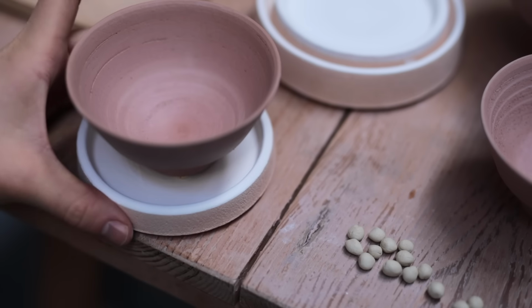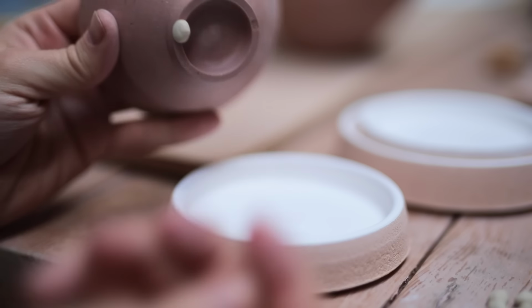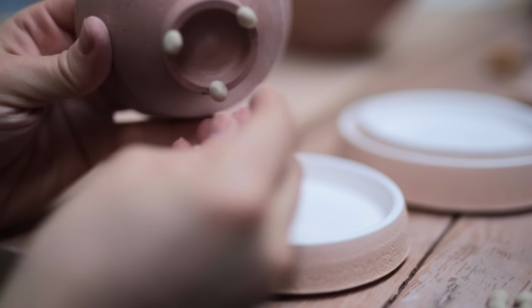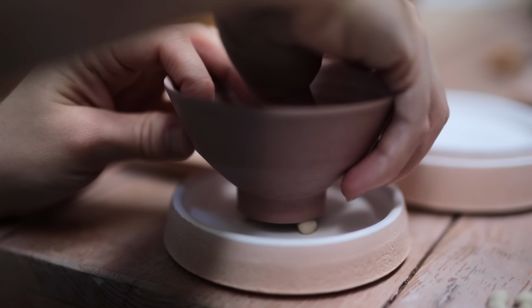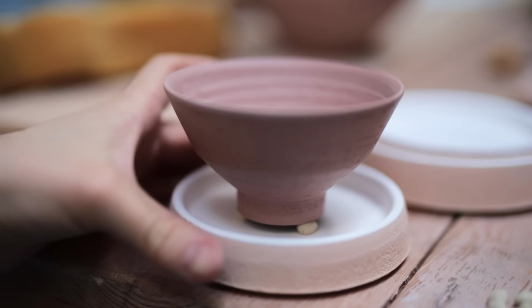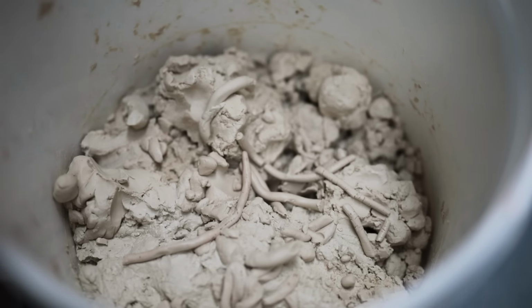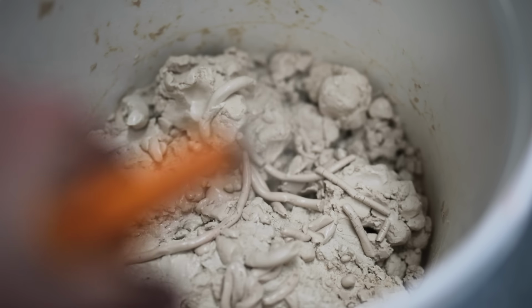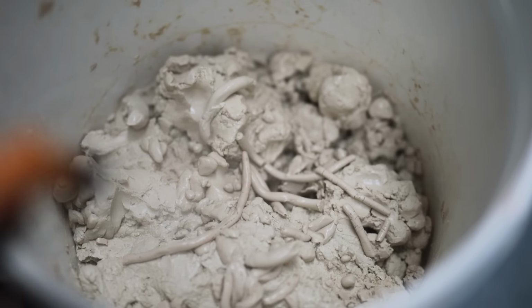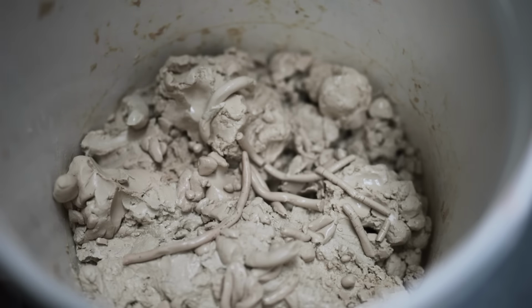This is actually a technique used for most atmospheric firings, such as wood, salt or soda firings. Simply put, in these kilns, the glaze is carried around by the flames in the atmosphere, and by having small feet like these that separate it from the shelf, there's no way the pots can fuse themselves down. Yet, if things do get very glassy and sticky beneath the pot, you often have to grind the waddings away carefully without damaging the pot itself.